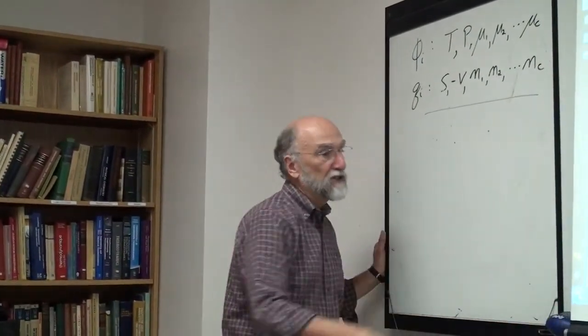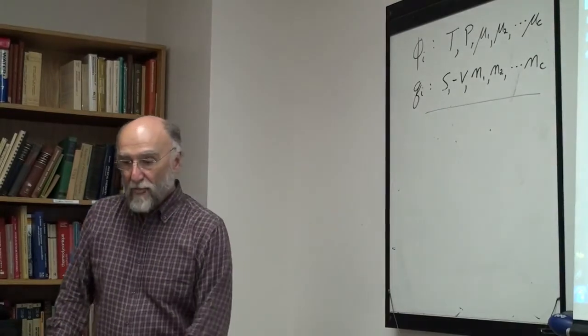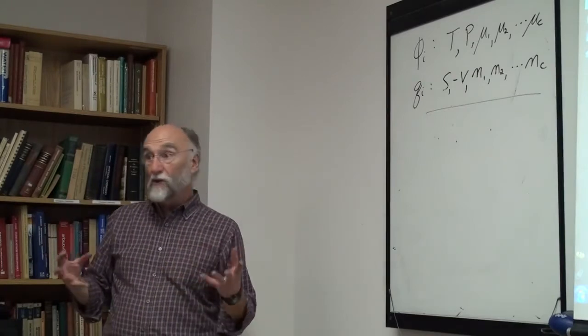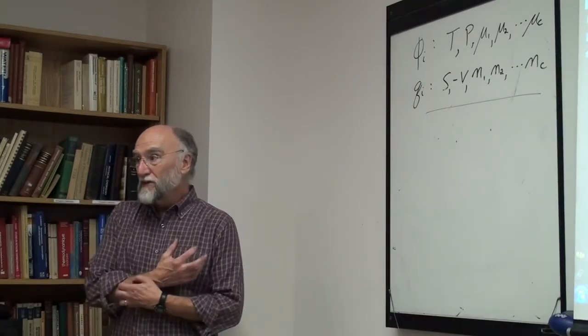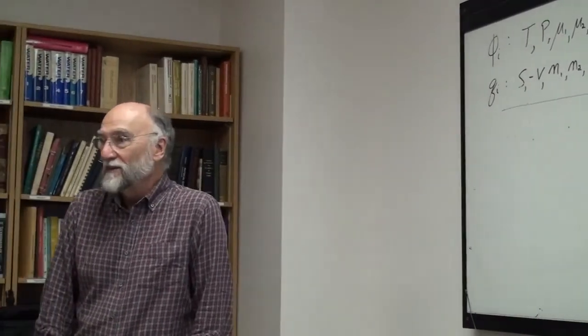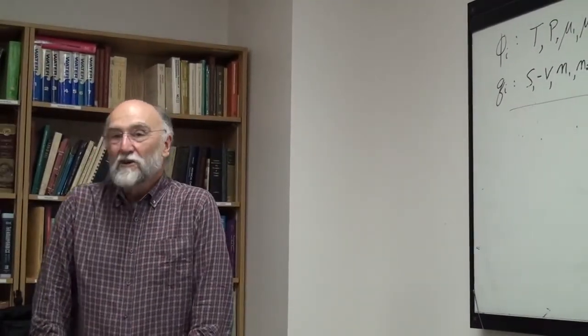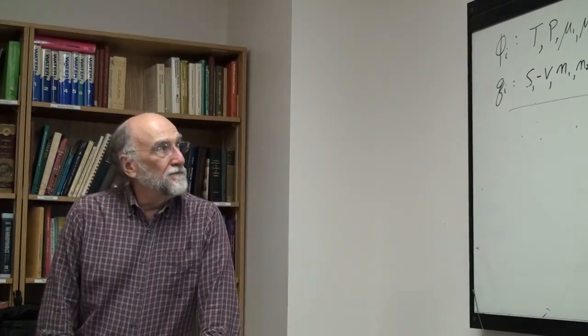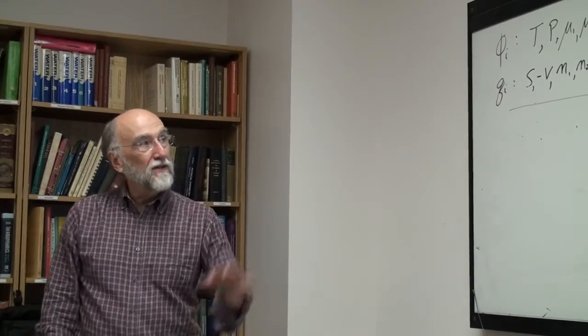Now there have been problems. I said these are sufficient conditions. A PV diagram for a substance other than water, or in certain regions, is okay, but you can't calculate it with FactSage. We have had many discussions, well maybe somebody would like to calculate it. You can't calculate it with the phase diagram program. You can calculate it with the Equilib program and save a whole lot of slices and then plot the thing up yourself using the Figure program. But you can't just go right to the phase diagram program and do it.